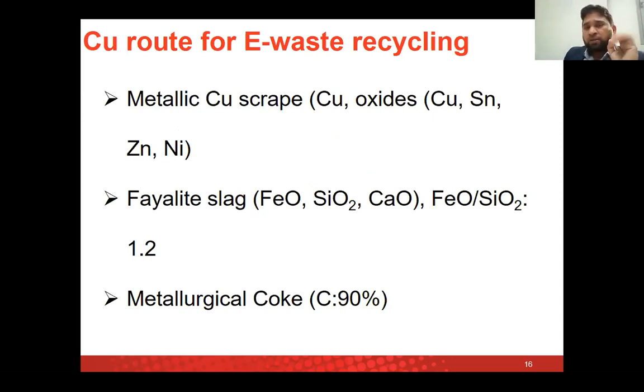During the copper smelting route, of course, we have a PCB. In copper smelting, we are not going to add ferrous material in there, like the plastic. No, we will only separate the printed circuit boards. Printed circuit boards contain copper, nickel, gold, silver. They also contain some silica, some alumina, but at the same time, the feed for the copper smelting route will be the metallic scrap, copper scrap.